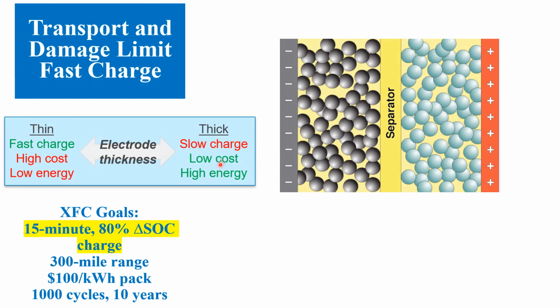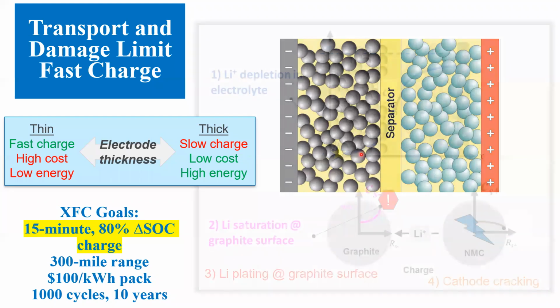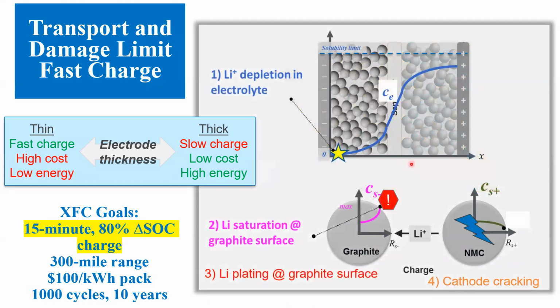First one, electrolyte gradient. Large concentration and potential gradient in the electrolyte phase to support high current result in non-uniform utilization of thick graphite electrode. In extreme cases, electrolyte concentration approaches zero, shutting off electrode utilization near the current collector. This may result in lithium plating and particle cracking near the separator.